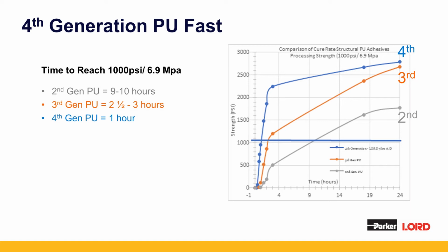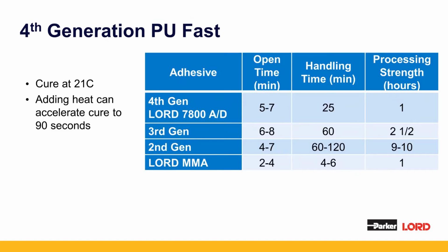So with the 2nd generation in gray line, even though there's 4 to 7 minutes of open time, it takes 9 to 10 hours to reach that strength of 1,000 psi, or the processing strength that we've indicated on the previous slide. 3rd generation polyurethane, again, 3 to 7 minutes of open time, takes between 2.5 and 3 hours. And the newest generation of adhesive, structural polyurethane, a 4th generation, takes only 1 hour to generate that processing strength of 1,000 psi.